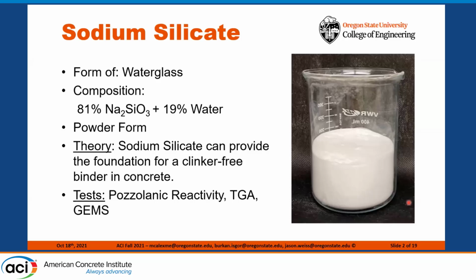We decided to start with sodium silicate in the form of water glass. The water glass we're using is 81% sodium silicate and 19% water, and in powder form. Our theory is that sodium silicate can provide the foundation for a clinker-free binder.